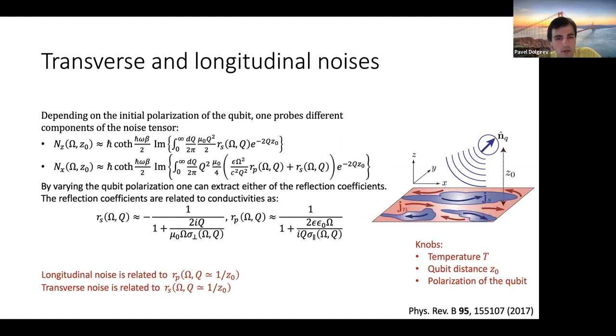So let me come back to the NV probe. Now what I envision is that I can prepare my initial polarization in various directions. For example, I can prepare it along the z-axis. This is a little bit complicated formula. It just tells me that the noise that I will be probing if I make such a setup will know only about the reflection coefficient of s-polarized waves. In contrast, if you prepare your initial qubit, say, along x-axis, then you will get contributions from both s-polarized waves and p-polarized waves.